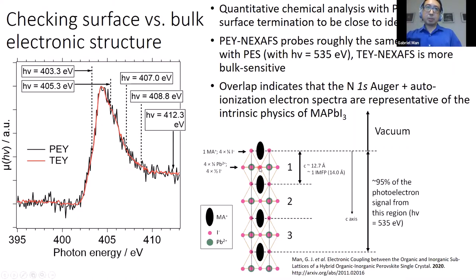So this surface model was derived by doing quantitative chemical analysis with photoelectron spectroscopy, and the error is about 10%. So we think it's a reasonably realistic model for what we're measuring.